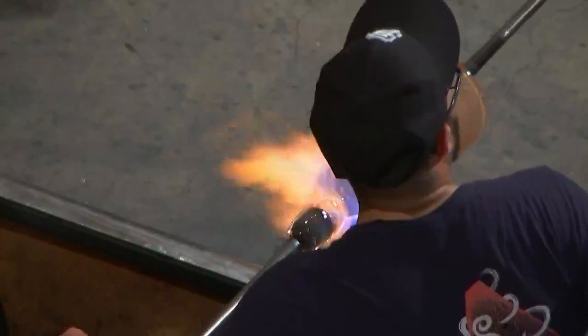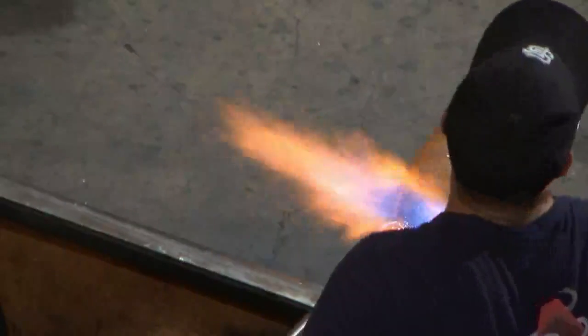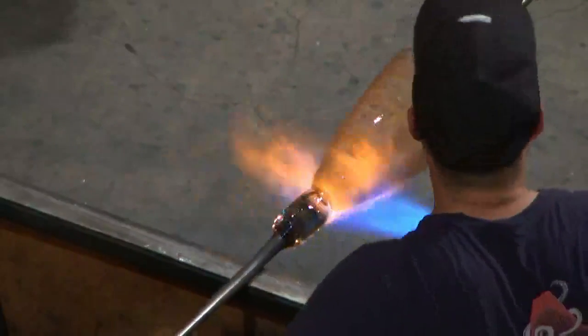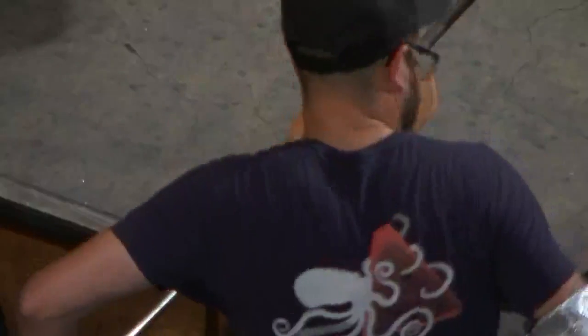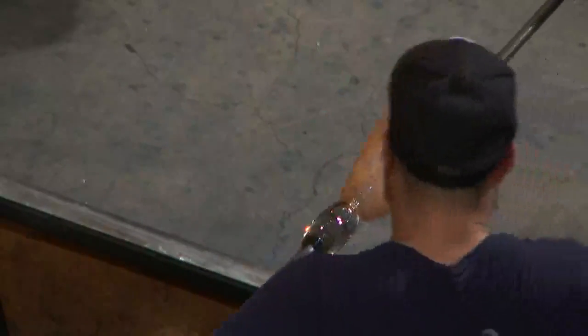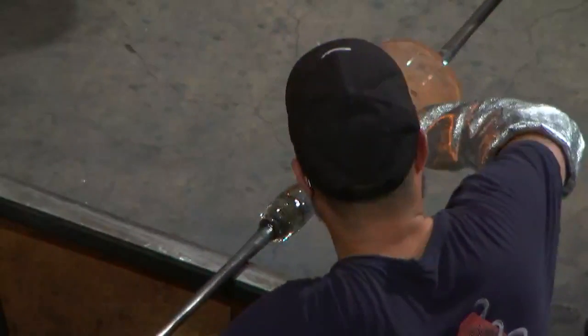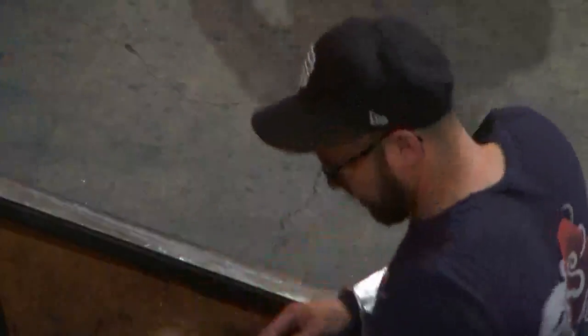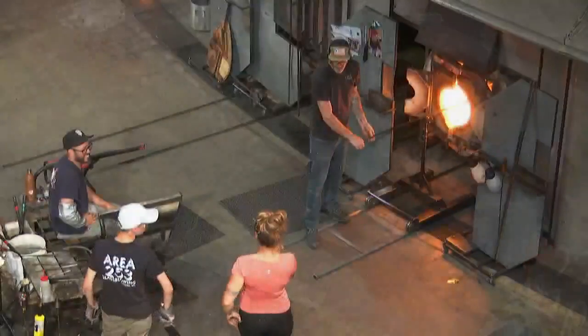Well, just like that, another vessel is complete here at the museum. Once again, if we leave our hot mass of glass out here, it'll get too cold too fast, and it can break, crack, or even explode. To prevent it from breaking, we will slowly cool it down over the period of the next several hours, 10 and a half to be exact.